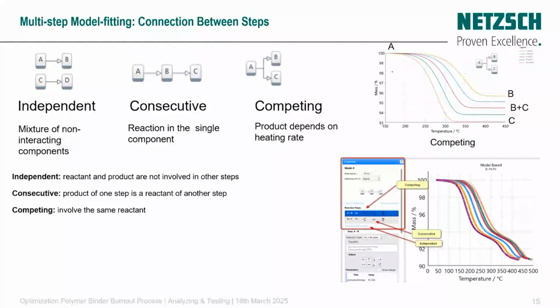And as you can see here, we have a reactant A, and we see that the product depends on the heating rate. We can see that the percentage of the mass loss is quite different at the end of it. So for the independent, the reaction and the product are not involved in the other steps. The consecutive, the product of one step is a reactant of another step, and the competing involve the same reactant.